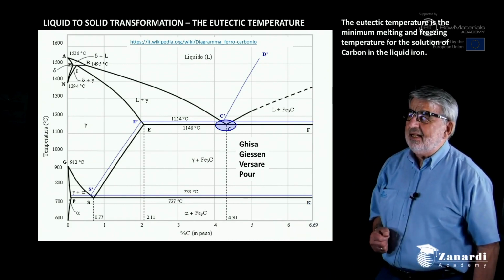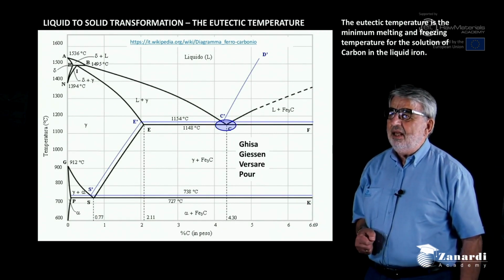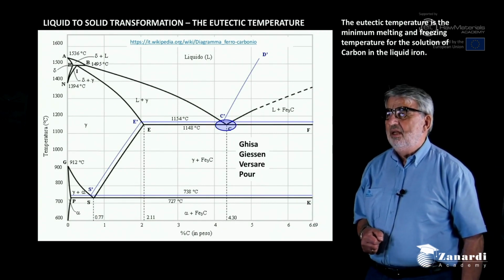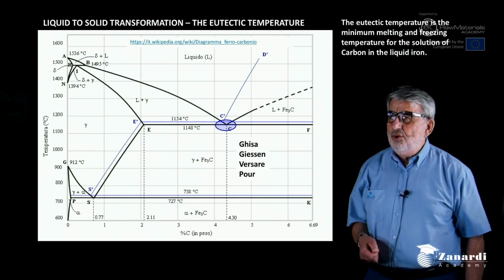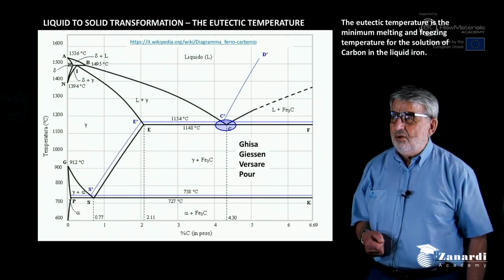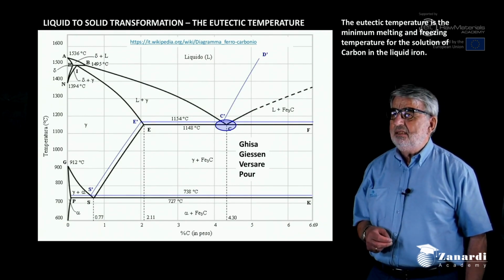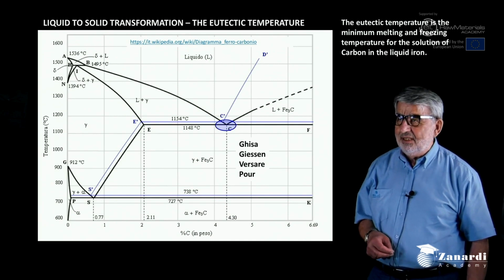The reason is that liquid iron is added with carbon, and as in all solutions, by increasing the solute concentration into the solution, the freezing temperature is decreasing.